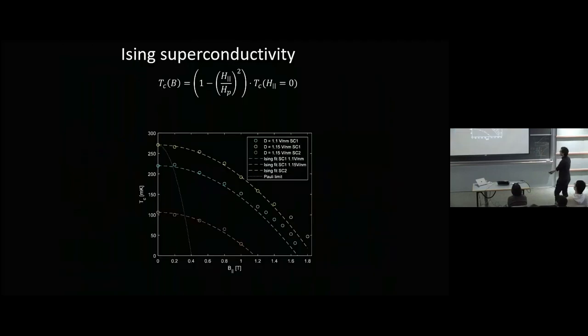And what's interesting, and I think maybe indicates why spin orbit is good, is that you have a system where you know exactly the strength of the spin-orbit coupling, and you can look at the Pauli limit violation and how it behaves. You see that in fact the TC is suppressed exactly. These are really zero-parameter fits. We measure TC at zero magnetic field, we apply an in-plane field, and we know exactly the strength of spin-orbit coupling, so we can put that into a pair-breaking formula and see that superconductivity is suppressed exactly the way you expect for an Ising superconductor.